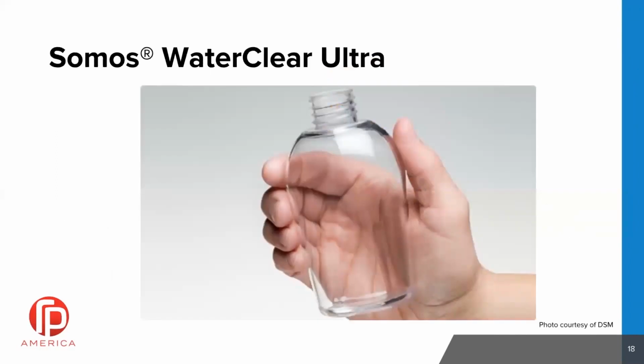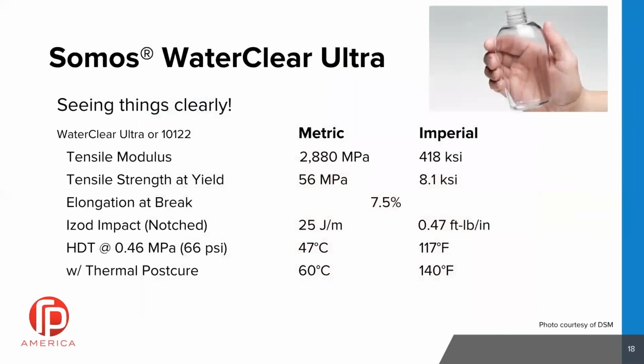All right, let's talk a little bit about some of the clear materials. This first one is 10122. So this has got good strength. The elongation at break is not nearly as, this material is not nearly as flexible at 7.5%, but it's got decent impact resistance. And this material can be thermally post-cured, and you can see the increase for the HDT from 117 up to 140 by running through a thermal cure.